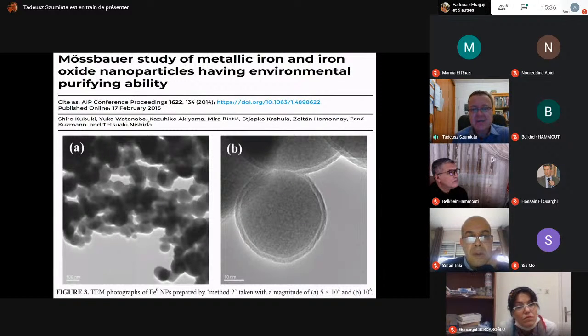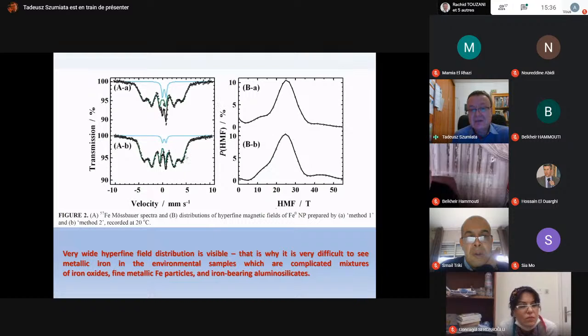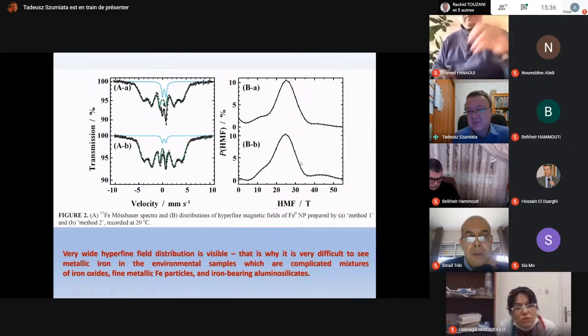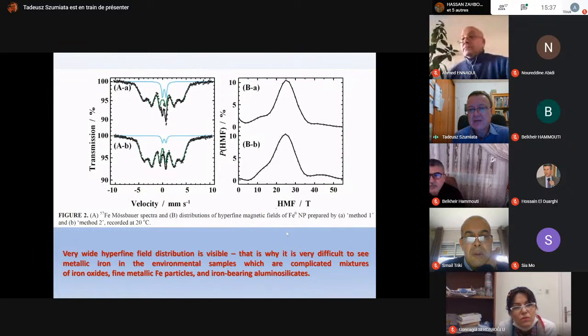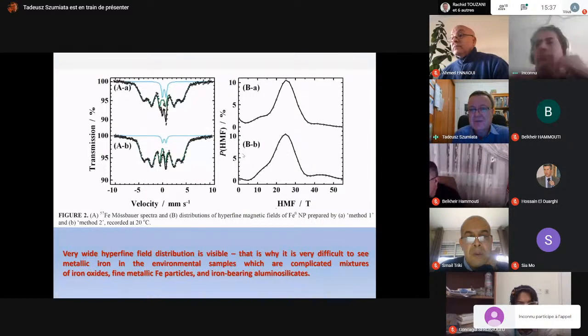And I have found also another work, not our work, which was devoted to artificially made nanoparticles of iron, and they also can see this very broad distribution of hyperfine magnetic field. That's why probably we see something similar in our environmental samples. And this is a reason why these components attributed to metallic iron is so wide and difficult for interpretation. Because here you have only iron, so it is obvious. But in our cases, these components are maybe 10% of the whole spectrum.